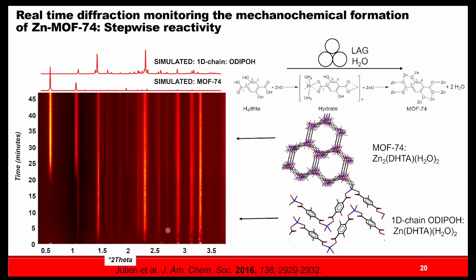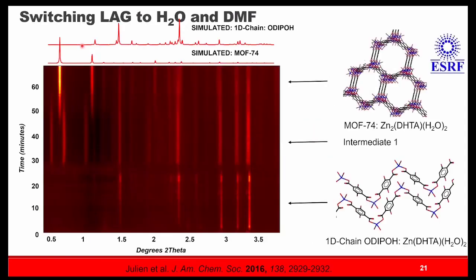And so what you see over time is we're just able to basically line up the simulated diffraction patterns with our experimental data. And you see that we get these 1D coordination polymers for about 20 minutes, and then you really get the emergence of the MOF-74 under grinding with small amounts of liquid, in this case, water and DMF.